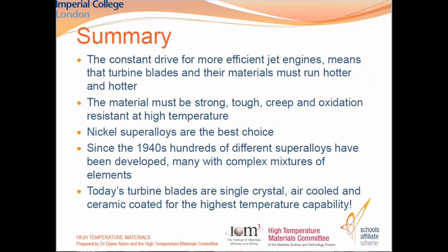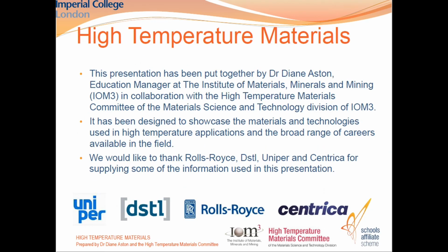So in summary, the constant drive for more efficient jet engines means that turbine blades and their materials must run hotter and hotter. The material must be strong, tough, creep and oxidation resistant up to high temperatures. Nickel alloys are the selected material for these applications, and since the 1940s, hundreds of different superalloys have been developed, many with very complex mixtures of elements. Today's turbine blades are single crystals, they're air-cooled, they're ceramic-coated, and they have the highest temperature capability.